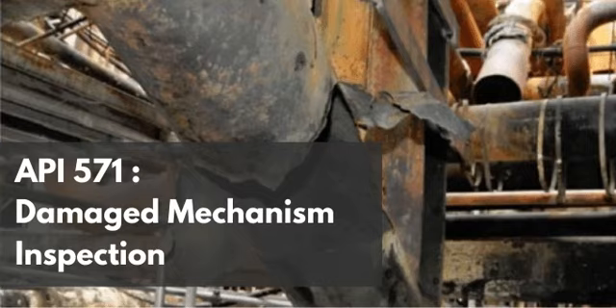Wow. The peak of this tensile stress occurs in the weld metal and the immediately adjacent heat-affected zone. Then the stress gradient gradually dissipates as you move outward into the base metal. By the time you're 2 inches away from the weld toe, the residual tensile stress has generally dropped below the threshold required to drive the intergranular cracking. Okay, that makes perfect sense for a weld. Yeah. But the guidelines explicitly contrast that standard 2-inch rule with a major spatial paradox.